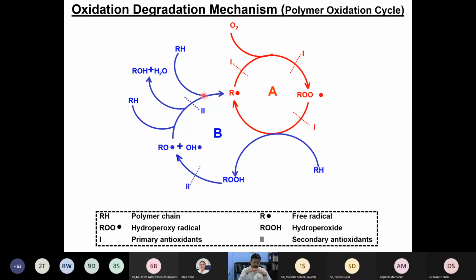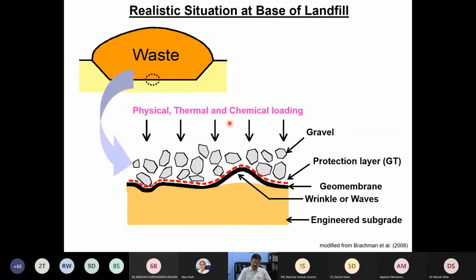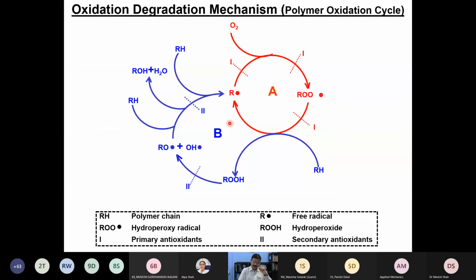In order to control these primary and secondary oxidation cycles, in the manufacturing process we induce primary antioxidants and we also induce secondary antioxidants. So we can always quantify the polymer oxidation process by measuring the quantity of antioxidant left in the geomembrane at any given point of time. That can be measured by using the oxidative induction time, OIT value. So that means, how does the oxidation happen in the case of a landfill? We know that this is the process by which it can happen.